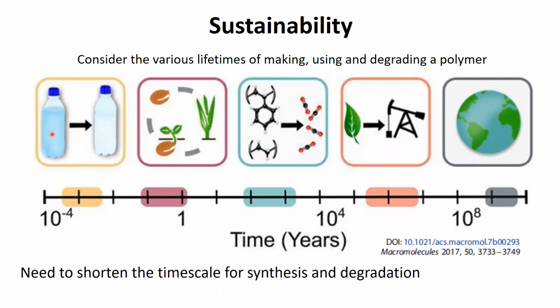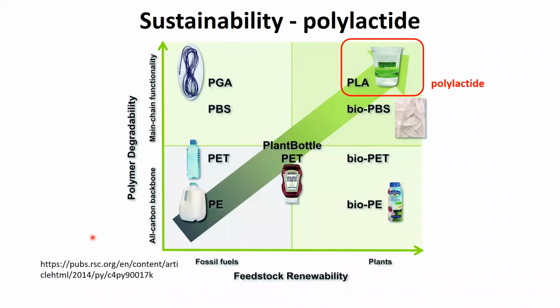The usable life of such plastics is such a short time scale that it then takes a long time for them to degrade to form feedstocks again and be able to close this loop. So the timescales of the synthesis and formation are so much longer than the use. So I think it's important to think about the lifetime of making, using, and degrading the polymer. And the key thing is we need to shorten the timescale for the synthesis of the raw materials and the degradation. The particular material that we use a lot in my group is polylactide.